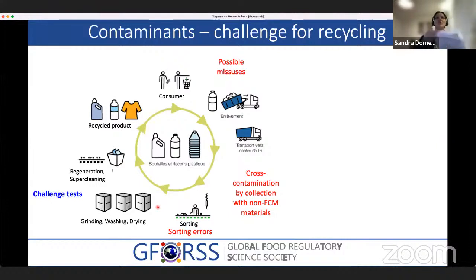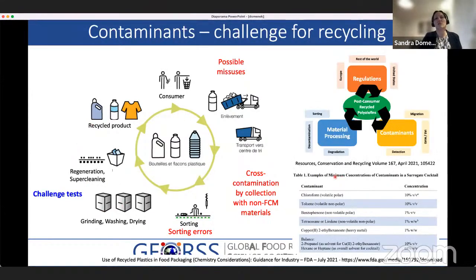The reason of this is, of course, the high contamination risk of plastics in an open post-consumer recycling because of contaminants coming from possible misuses, from cross-contaminations by the collection with non-food contact materials, and from sorting errors. So in the aim to be able to recycle back the plastic to food contact material, the EFSA is imposing specific processes, and you will need to show that you have regeneration and super cleaning technologies which are ensuring food safety over challenge tests. And the challenge tests are also asked for by the FDA, for example, here, which shows you what you will need to do in order to be sure that your cleaning strategy is then safe for the plastic being used by the consumer as food contact material.